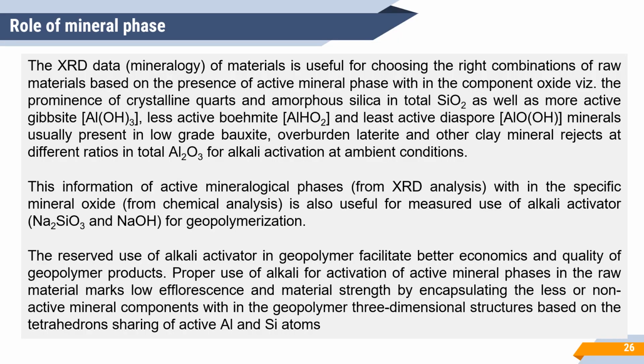It was observed that the XRD data or mineralogy of a material is useful for choosing the right combination of raw materials based on the presence of active mineral phases within the component oxide. For example, the prominence of crystalline quartz and amorphous silica in total silica, as well as more active gibbsite, less active boehmite, and least active diaspore in minerals usually present in low-grade bauxite, overburden laterite, and other clay mineral rejects at different ratios in total alumina for alkali activation at ambient condition.